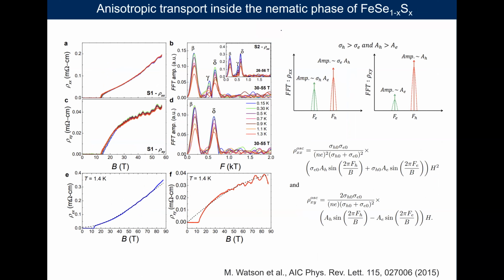One more unusual effect of this anisotropy also occurs in the quantum oscillation if we measure the rho xx component versus rho xy. If you do a Fourier transform, we see that the rho xx Fourier transform has 3 different features. These are measurements up to about 90 Tesla, so very high magnetic fields. But if we measure the rho xy component and do its Fourier transform of the quantum oscillation spectra, we are missing one of the pockets.